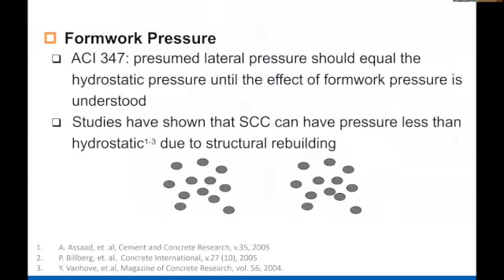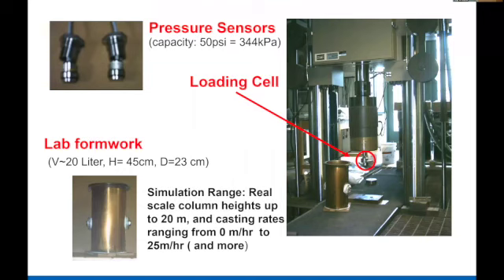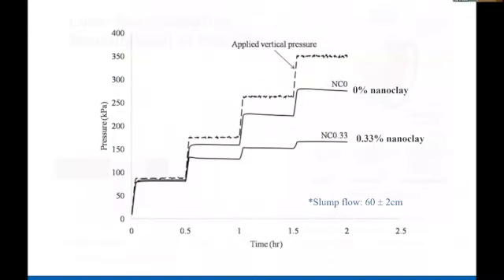What happens is that when you stop vibrating or pumping concrete, the particles coagulate and they can transfer stresses, which we call thixotropy. Like blood is thixotropic. If you bleed, blood coagulates and it doesn't continue to flow. So what we did is we made cast samples of concrete with and without nanoclay and measured both the vertical pressure and the lateral pressure, which would be the formwork pressure. And I want to show you some results of the effect of nanoclay.